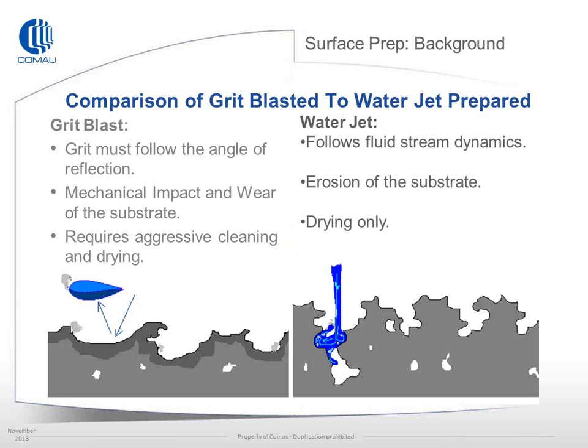The second process that's really taken off is water jet. This process produces a very clean and complex surface, also difficult to measure and assess, but it has a very high quality surface and very high adhesion results. The one shortcoming with water jet is its ability to ablate and open up any casting issues, particularly in die cast. But those are things that can always be evaluated and developed. But for now, the trend seems to be moving towards, from our side at least, to a mechanical surface roughening.